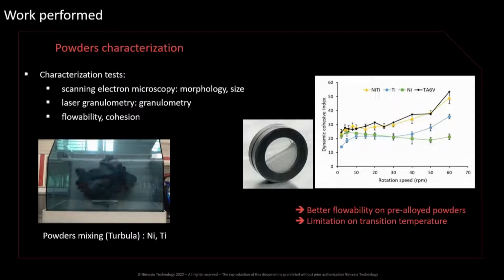And then we calculate the flowability using this small wheel. And the result was that for separate powder, as you can see on the green and blue curves, the flowability is lower than for pre-alloyed powder, and then our reference, which was titanium. But okay, we say the flowability is not as good as our reference, as titanium, but let's try it.